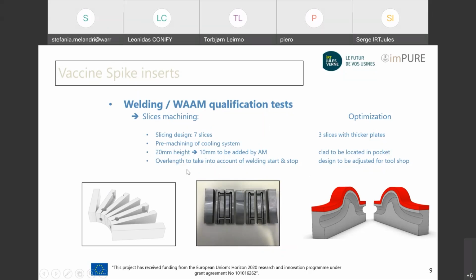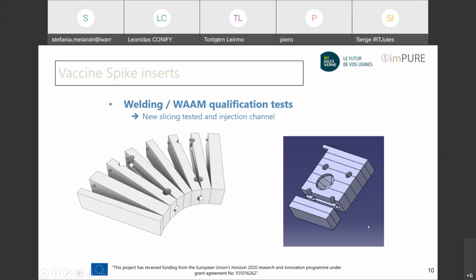The blocks were assembled by 20 millimeter high elements, and at the end we add 10 millimeter by additive manufacturing, by WAAM, and the overlength to take into account the welding start and stop. So as I say, it was not the optimized solution, because the optimized should have been the 3 slices only, a clad, only a local clad, to be located in one pocket, in the top pocket, and the design can also be adjusted to be manufactured directly in the tool shop.